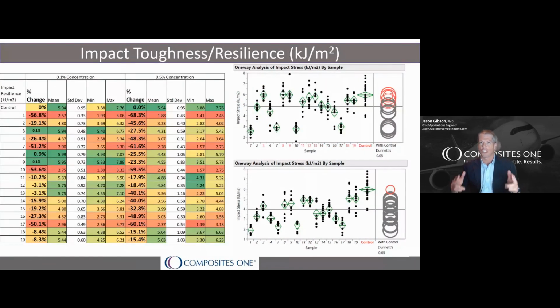So if we look at just the toughness results for both loading levels, you can see again that the 0.5% loading shows a lot of red and orange in the percent change, and none of that is good. But in the 0.1% loading, you'll see a number of green results that are good, with sample 9 being one of them, and sample 18 being yellow at an 8% change. But that 8% change is not statistically significant for us to know that it definitively has an impact.